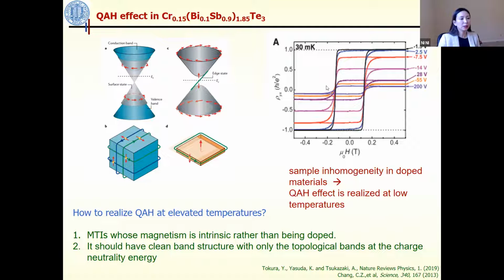So in 2013, QAH was experimentally observed in chromium-doped topological insulator thin film below 30 millikelvin. The thin film actually orders ferromagnetically below 15 Kelvin. However, the effect was observed below 30 millikelvin. This low temperature required to realize such a QAH effect is actually due to the sample inhomogeneity in doped materials. So then the question is how to realize QAH at elevated temperatures.